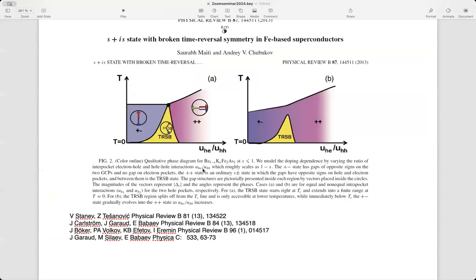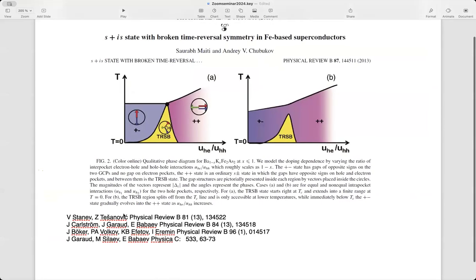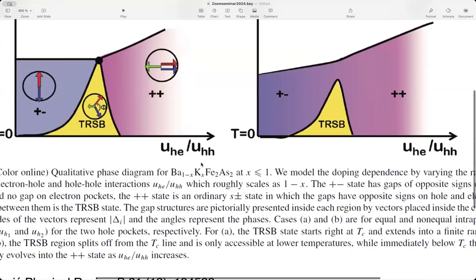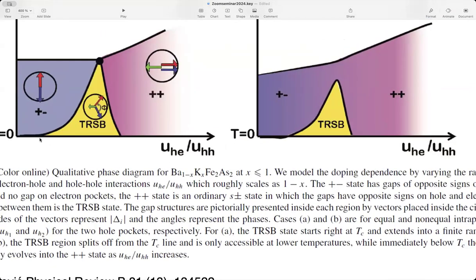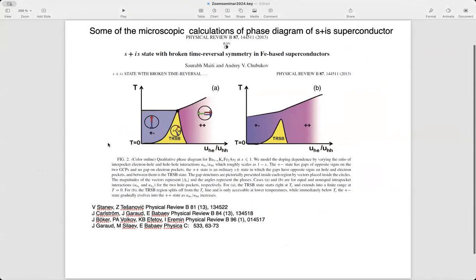And this was a fairly old prediction, I think first from 2010. It was considered as a function of doping, as a function of the ratio of these two, of x, of doping. So at some point you can have two gaps, you can have three gaps, you have either a pi phase difference where the system breaks only one symmetry, or you can actually have a frustration and then twofold degenerate locking between these phases. And then we